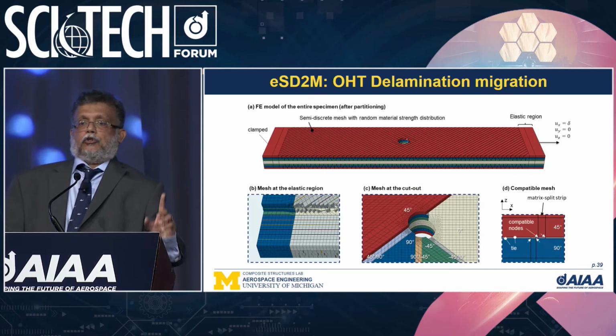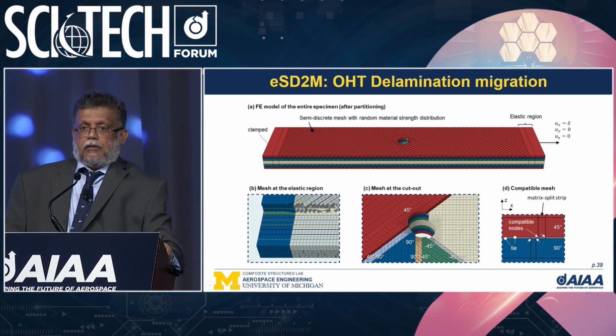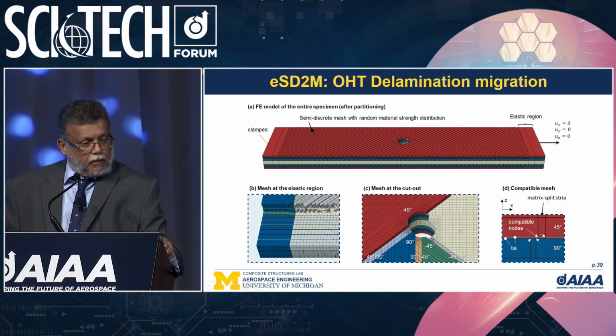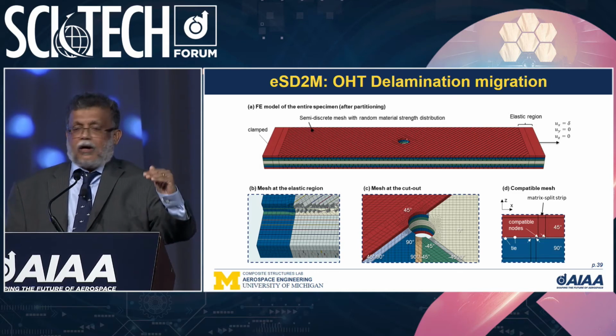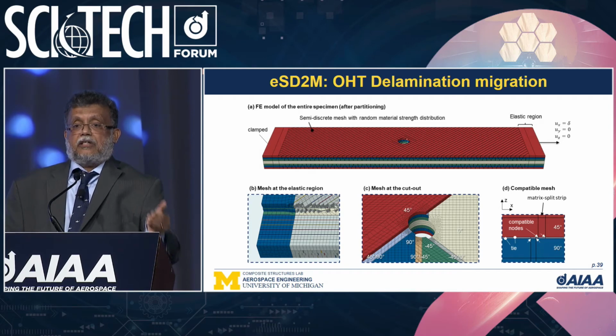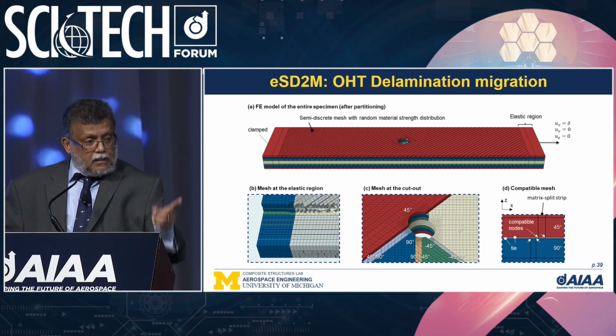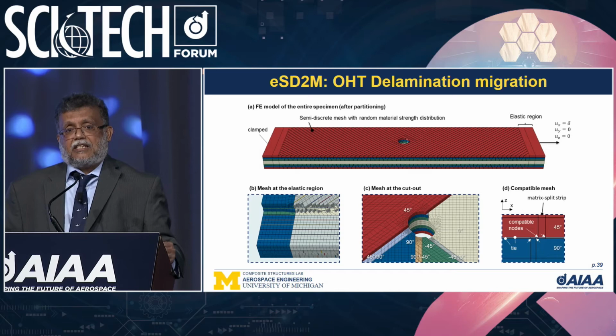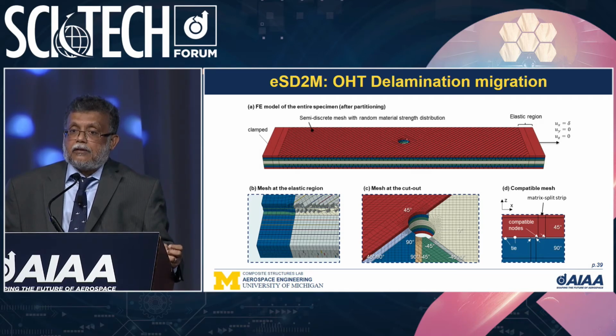Finally, I want to show you a very challenging problem: delamination migration. Delaminations that start at one layer migrate to a different layer because they are energetically favorable. Here I am showing you these laminates where the testing was done at the University of Bristol by Stephen Hallett, Michael Wisnam and their co-workers.